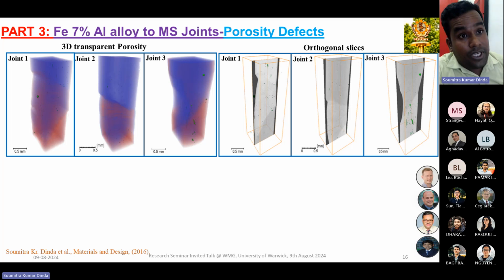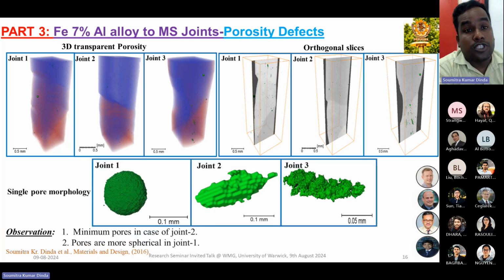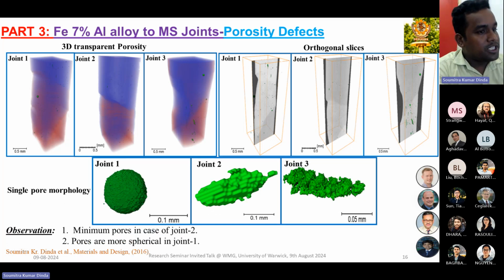Now, if you see, the pore sizes are very different, and the shapes are also different. If you look at the individual pores, the biggest one, this is the biggest pore. In the case of joint 1, we see circular or spherical pores. Joint 2 and joint 3 have irregularly shaped pores.